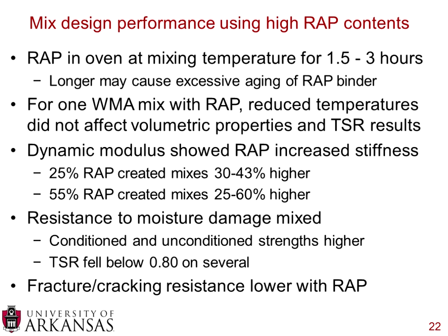So within literature, there is not 100% consensus on what to do with the RAP. They here in this report said, make sure you're using the mixing temperature, but you do not have the RAP in the oven for more than 3 hours. If you have the RAP in the oven for more than 3 hours, you can continue to age that RAP binder, which will change the properties of it.